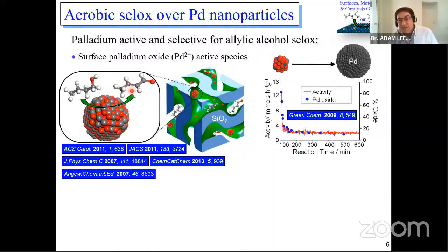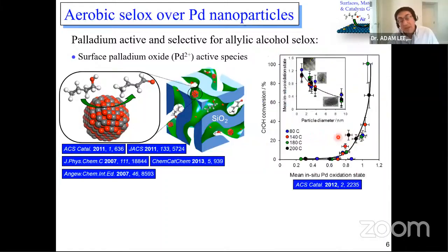So what we've shown is the active site responsible for these transformations is actually a metal oxide, palladium oxide. So small palladium oxide nanoparticles are very active for these transformations. And as the catalytic reaction proceeds, the catalyst becomes reduced and it makes large metallic particles, which have a very low background rate. So palladium oxide is good and palladium metal is quite bad for this chemistry.